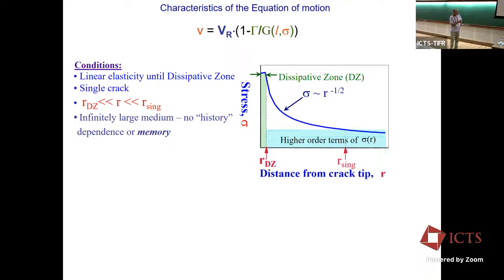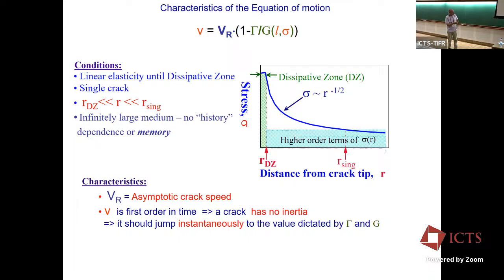the velocity here is an instantaneous function of the length of the crack. There's no acceleration term here. It's almost like, well, okay, first we have this asymptotic speed. Now V is first order in time, or with the crack. So the crack has no inertia. It's almost like a massless particle.